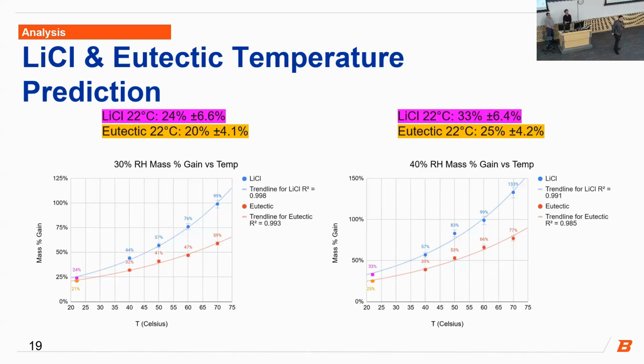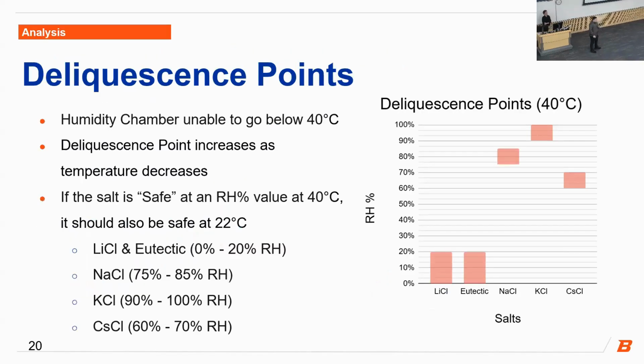So this is great for lithium chloride and eutectic, but what about our other salts, our cesium, potassium, and sodium chloride? What we need to figure out is that if they do not deliquesce at 30 and 40% relative humidity, when do they deliquesce? So an important note is that our humidity chamber is unable to go below 40 degrees Celsius. However, we do know that as temperature decreases, the deliquescence point increases. In other words, if we know that sodium chloride does not deliquesce below 75% at 40 degrees Celsius, then it absolutely won't at 22 degrees Celsius.